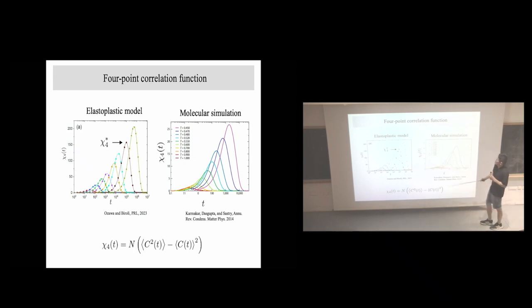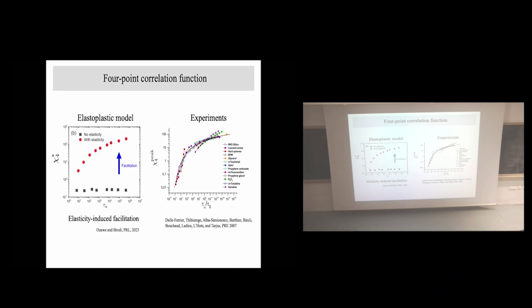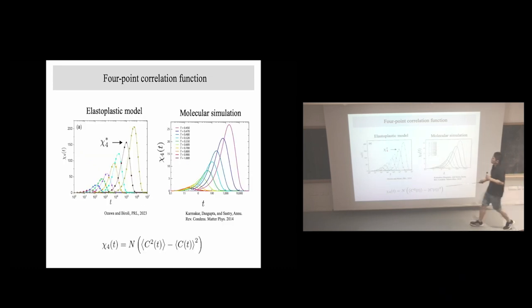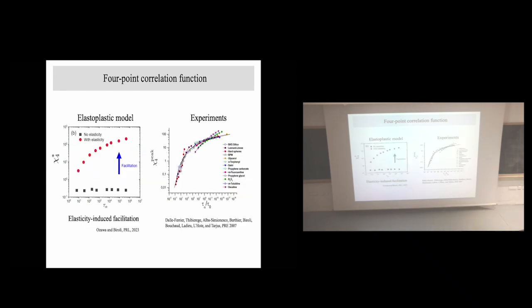So our elastoplastic model successfully reproduces the temperature and the time evolution of Chi4 compared with the real molecular simulation data. Okay. And also, we look at the peak value of Chi4, which corresponds to the size of the dynamically correlated region, and we plot this as a function of relaxation time, because this plot is inspired by real experimental observation or estimation.